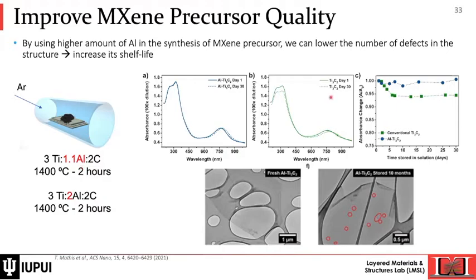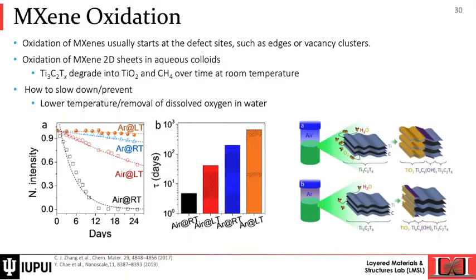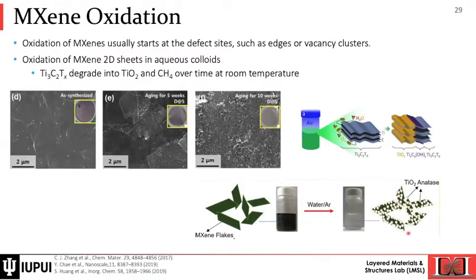the precursor will have fewer defects in the structure, and fewer defects in the precursor means fewer defects in the structure of MXene and increases the shelf life of MXene. Here you see that after 30 days, there is really no change of properties. And here are the 2 TEM images of a fresh MXene, and after 10 months of Ti3C2 stored in water, and you only see small amounts of defects forming on the flake. Remember, if we are not using this modified precursor with 2 moles of aluminum, only after a few days, basically, MXene will get oxidized.